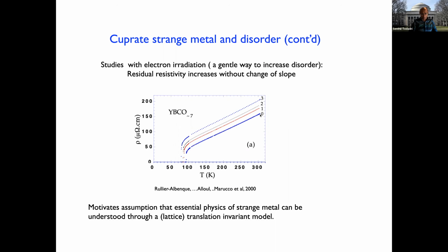So what you see in the data is that, it's all done in the same sample, and 0, 1, 2, 3 refer to the data taken after different exposures to the irradiation, right? Different exposure times, right? So the slope doesn't change, but the intercept changes, right? The curves move parallel to each other, right? So you're increasing the disorder by increasing the irradiation time, and you're not changing the slope. The only thing you manage to change is the residual resistivity, right? This again strongly suggests that the slope is insensitive to disorder, right?